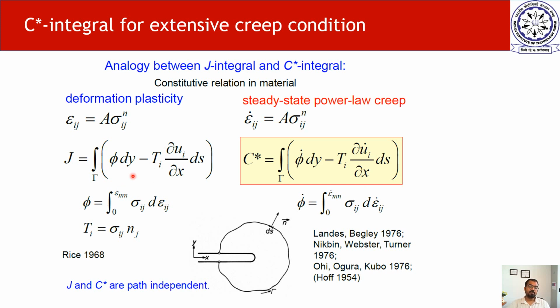So we have a close cousin of J integral, which is called C star integral, and there is another one which is CT integral, and the basic difference is that some of the terms in the J integral have been replaced with the rate of change of those values. For example, phi dot is the rate of change of strain energy density calculated using this formula, and U dot is the rate of change of displacement. But the point to note here is that C star is not equal to the rate of change of J integral. So J for a static crack for a non-linear elastic material does define crack driving force, but C star is not related to the crack driving force at all.